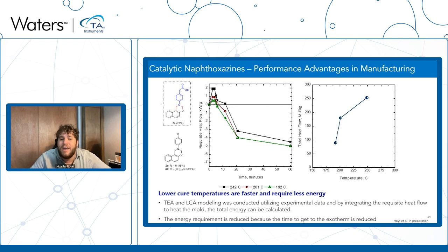you can get dramatic reductions in the amount of energy that you need to operate this process. So thus, you should get savings in energy, greenhouse gas emissions, and costs to ultimately manufacture these materials, simply by lowering the cure temperature by using bio-derived resources. So that was the first story, very quickly done, showing how we extensively used our DSC to show that we can get performance advantage in naphthoxazine-based thermosets.